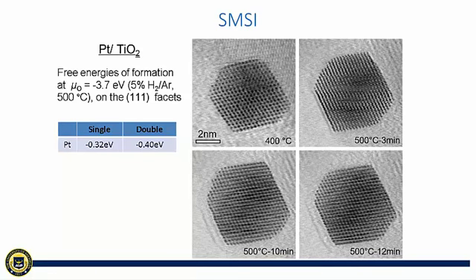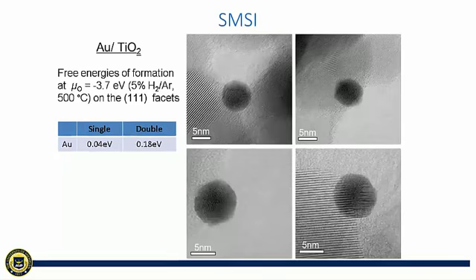We also did a control experiment on platinum TiO2. The theory says the overlayer will also be energetically favorable, and we did see the formation of the crystalline double layer at exactly the same condition. But gold TiO2 is another story. The calculation says that the formation of the overlayer will not be energetically favorable, and as a result, we didn't see any layer formation on the gold particle under the same atmospheric condition.